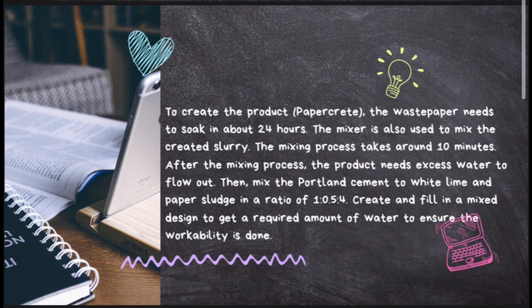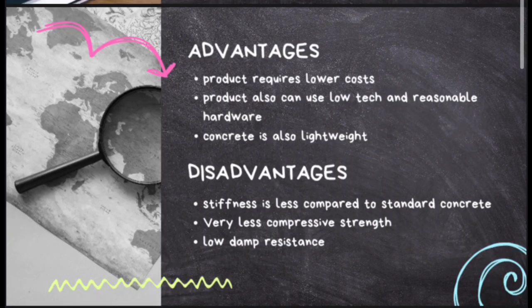A mixer is also used to mix the slurry. The mixing process takes around 10 minutes. After the mixing process, the product needs excess water to flow out. Then, mix the Portland cement with white lime and paper sludge in a ratio of 1:0.5:4. Create and fill a mix designed to get the required amount of water to ensure the workability is done.